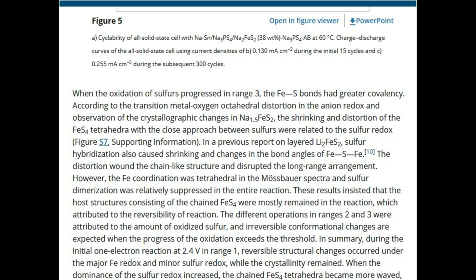However, the Fe coordination was tetrahedral in the Mossbauer spectra and sulfur dimerization was relatively suppressed in the entire reaction. These results indicated that the host structures consisting of the chained FeS4 mostly remained in the reaction, which was attributed to the reversibility of the reaction. The different operations in ranges 2 and 3 were attributed to the amount of oxidized sulfur, and irreversible conformational changes are expected when the progress of the oxidation exceeds the threshold.